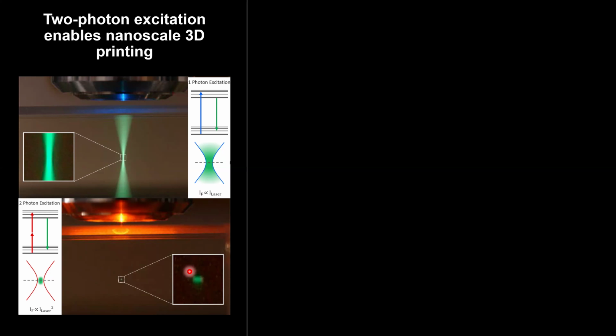Yeah. I think I understand that the two-photon transition is very nonlinear and you can focus it tight, and it drops off laterally pretty quickly. Yeah, so the PSF you're going to get here is essentially equivalent to any standard PSF from a lens. So say if it's roughly 200 nanometers laterally, that's usually roughly like 500 to 600 nanometers axially. Yeah, so it is somewhat anisotropic.